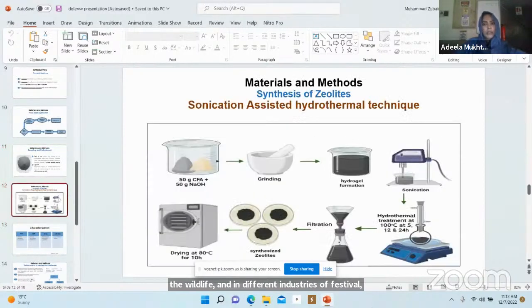In this, we will do a sonication-assisted hydrothermal technique. We will take 50 grams of coal fly ash and 50 grams of sodium hydroxide, grind it, and make a hydrogel. This hydrogel is treated with sonication. Then we will apply the hydrothermal technique at 100 degrees Celsius for different times. Then we filter and synthesize the zeolites, and we will dry them in an oven.